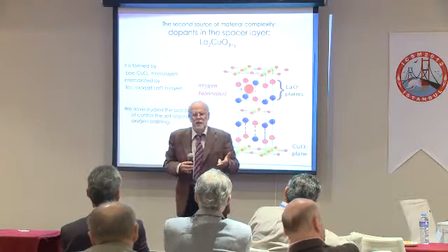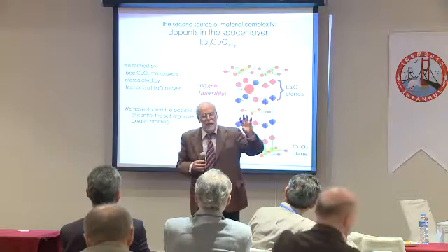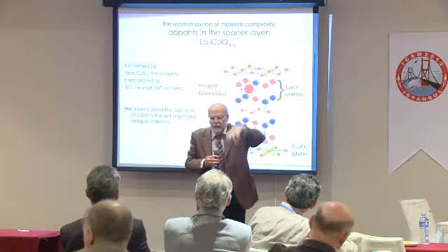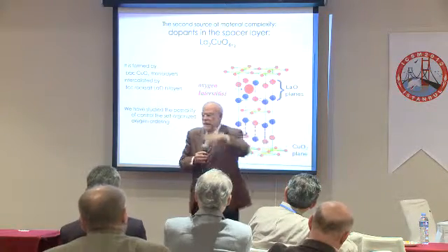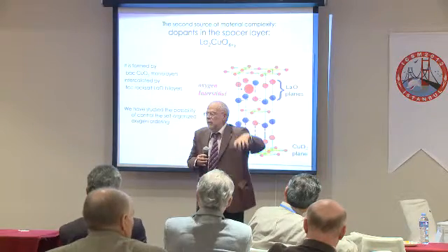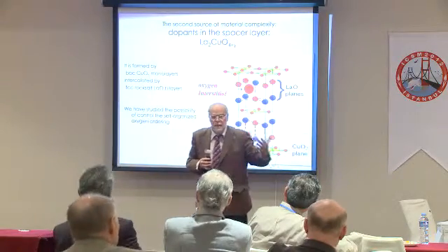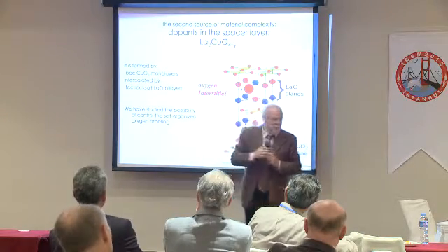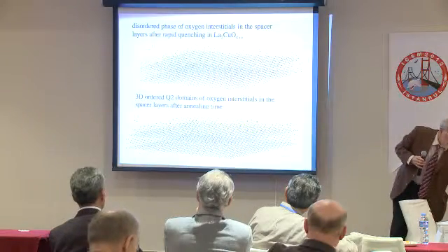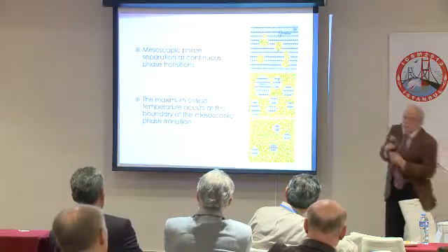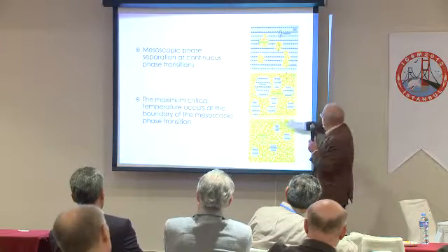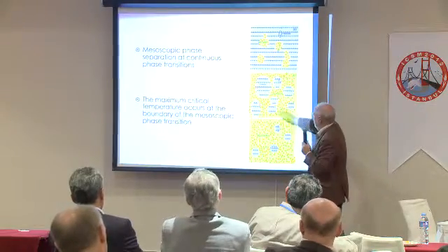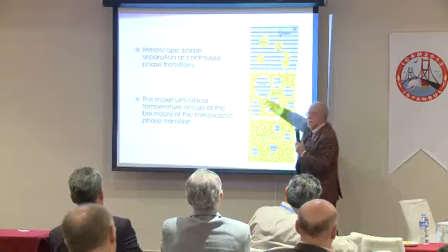Because nano X-ray diffraction allows us to see in each module that you have a long-range order, the formation of patches of different striped bubbles. Because each striped bubble will have a superlattice peak, will have a diffuse scattering peak. So I can see the different patches by going point by point with X-ray diffraction. I have an X-ray beam and I go here, and then I see X-ray diffraction because of the lattice organization. Then I go here, I don't see anything. Then I go here, I see something else.